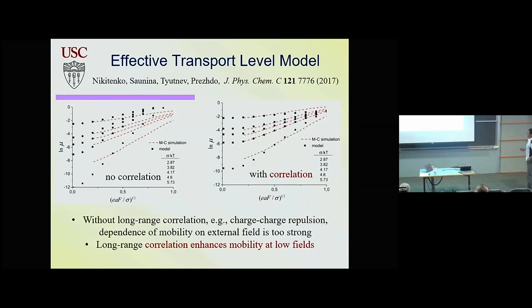And simple descriptions like that give you straight lines. So let's see. I'm comparing here Monte Carlo simulations versus a model, and here is the simple model, and this is the advanced model that my collaborators developed. What happens here is that I'm plotting mobility versus applied field, and you have straight lines, but then you have tails. In this example, when the field is very weak, you have a decay in the transport, but the decay is too fast if you have a simple model.